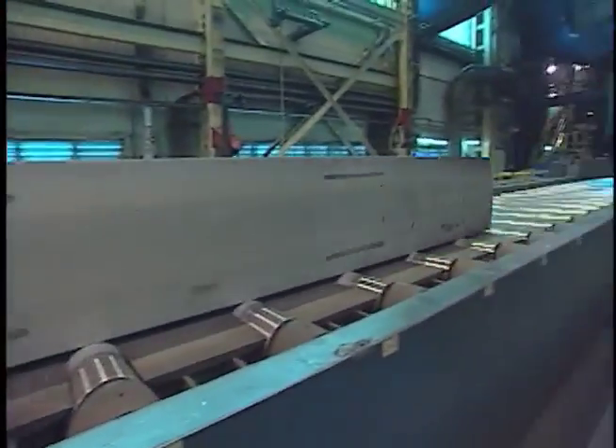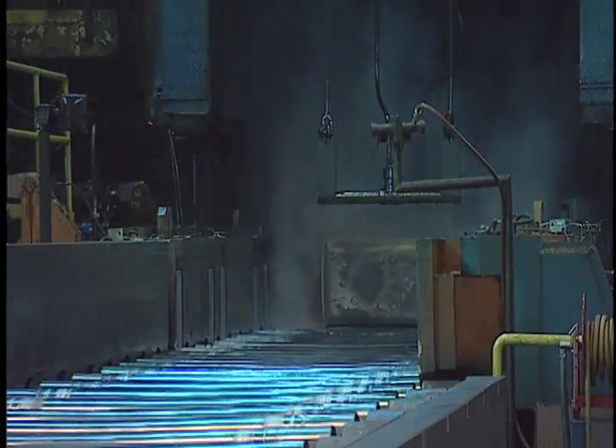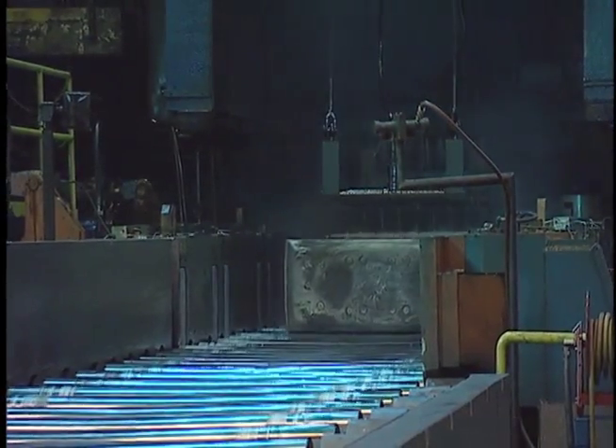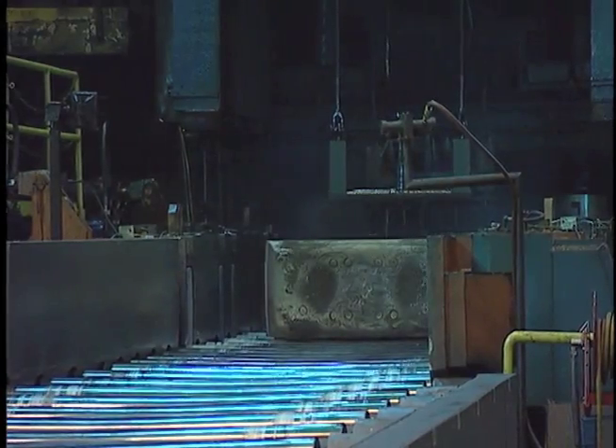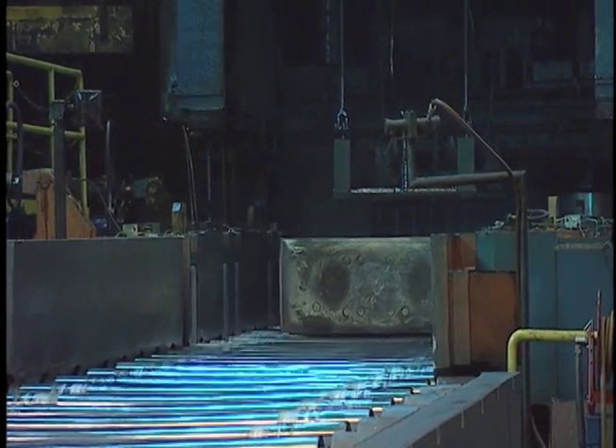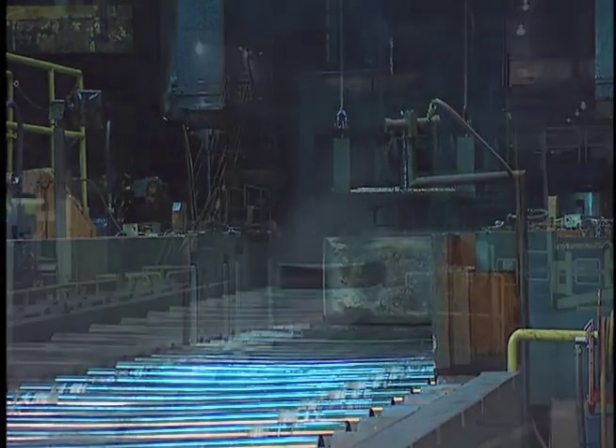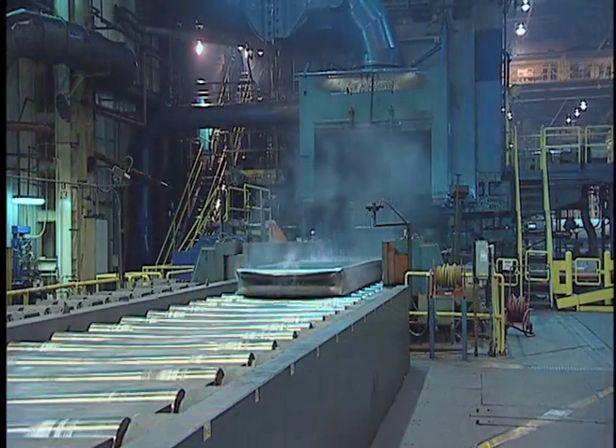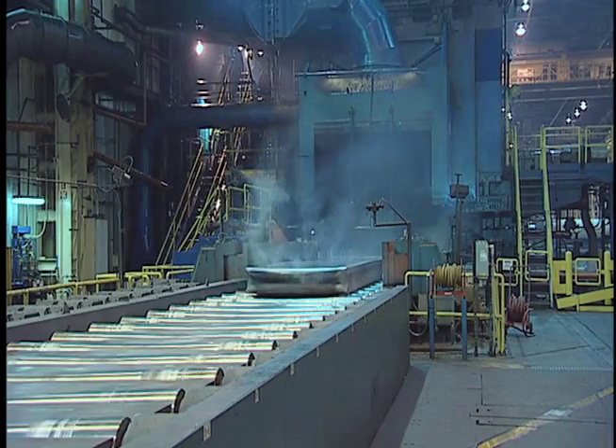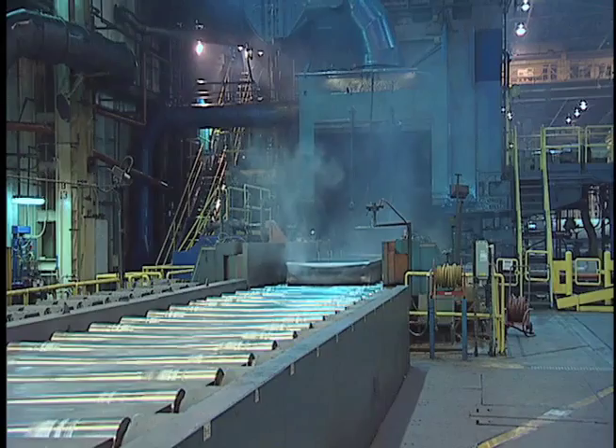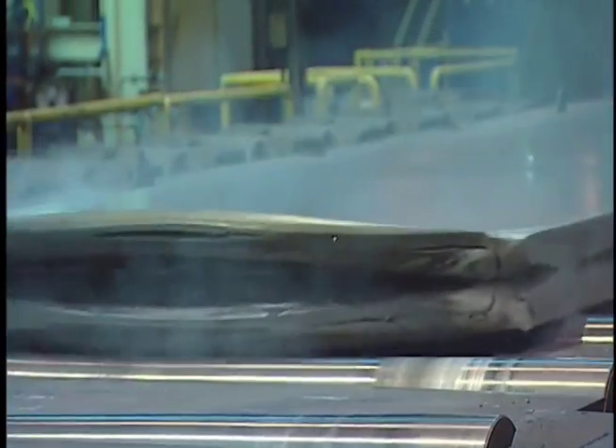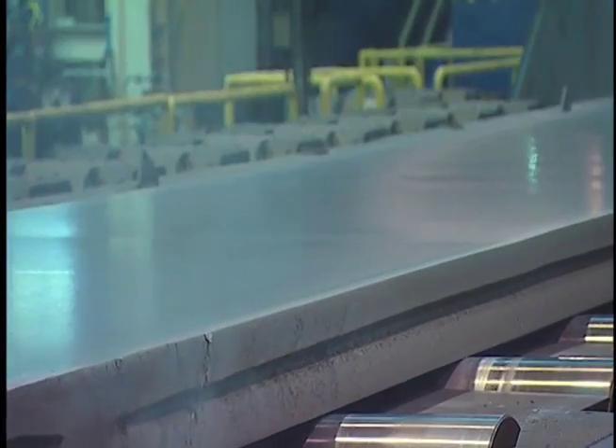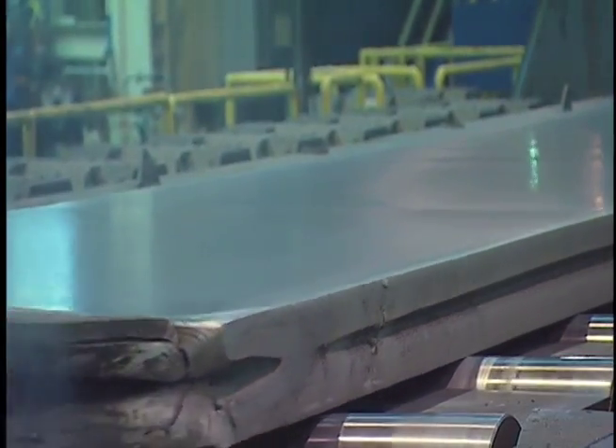Once the ingot has reached the reversing mill, the pulpit operator will begin forcing it through the mill, and the force of mill rolls will begin to reduce the thickness of the ingot. Additionally, force is applied to the sides of the ingot, which causes it to increase in length but stay the same width. Can body ingots will have to have approximately 17 passes to reach the desired thickness, and can end ingots will have approximately 27 passes.